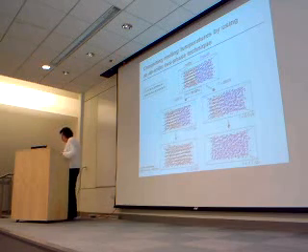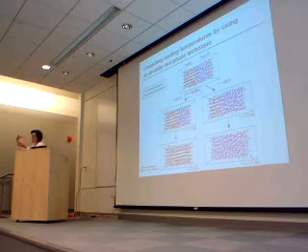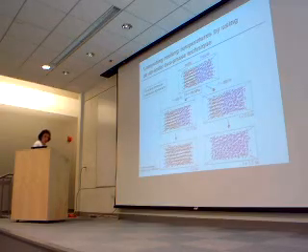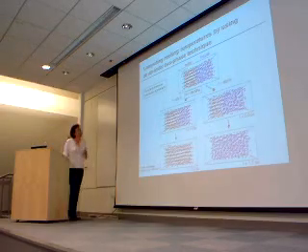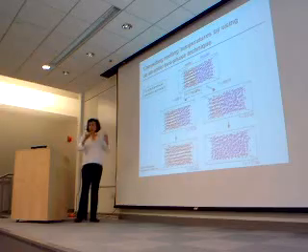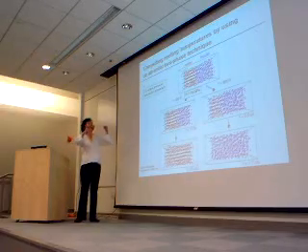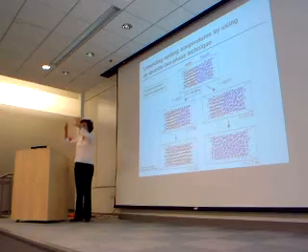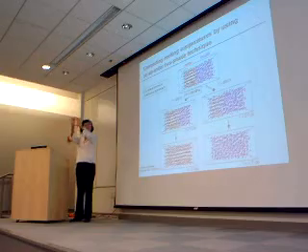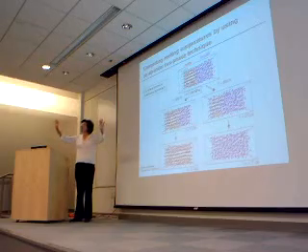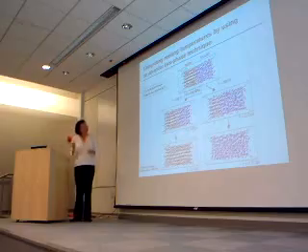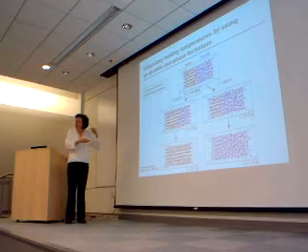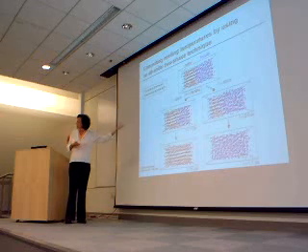You use all the techniques we talked about this morning. You heat up your system, you melt your system, and you prepare it in a liquid simulation. Then you use the technique we talked about to do constant pressure molecular dynamics, and you set the pressure of your solid and your liquid, and you put your solid and liquid in contact with each other, and you let the system go. And at different pressures, so you choose the pressure, you see the phase that wins.